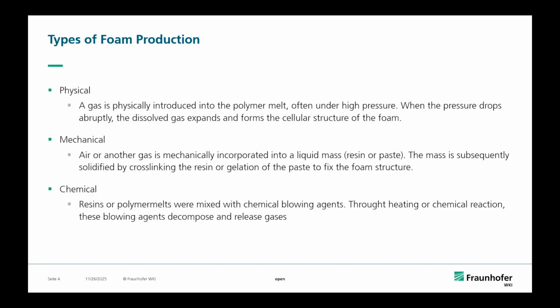You can also do a mechanical foaming process. Then the air is mechanically incorporated into this polymer resin or paste. And then the mass will be put into a solid state with a cross-linking agent, so you fix the foam structure. An example is a mattress, for instance, with latex. And finally, the chemical foam: you have resins or polymer melts, and you mix them with blowing agents, and then by heating or chemical reactions, these blowing agents decompose, release the gas, and finally you have the foam. The example I will tell you about today is the final one, the chemical foam.